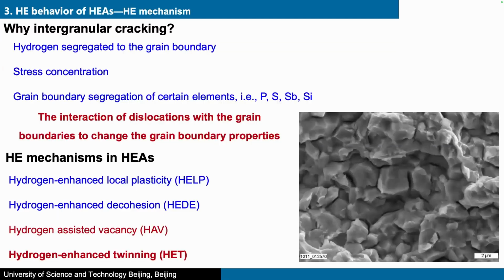And also we come to why intergranular cracking is observed in high entropy alloys. There are many reasons, such as stress concentration, hydrogen segregated into the grain boundaries, and others. But what are the hydrogen embrittlement mechanisms in high entropy alloys? Sometimes we think HELP, HEDE, and hydrogen assisted vacancies also exist. And the very important reason maybe is hydrogen enhanced twinning in high entropy alloys.